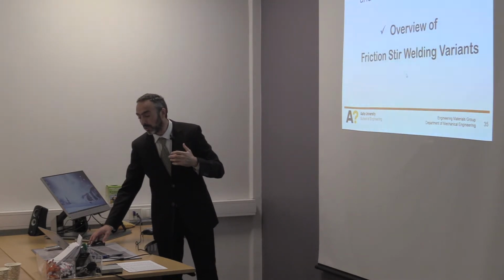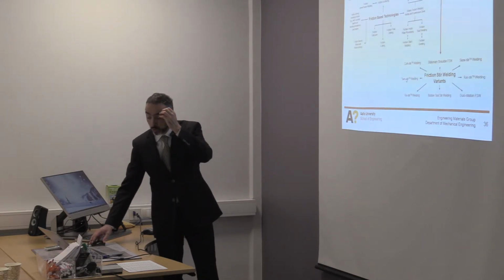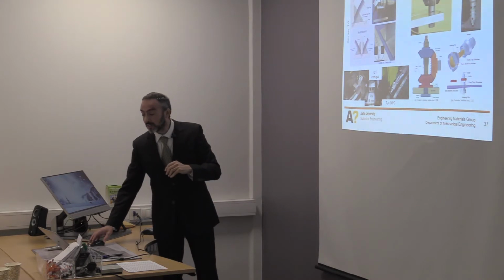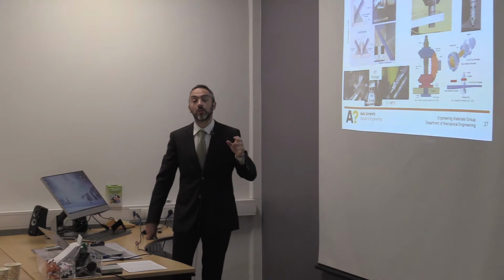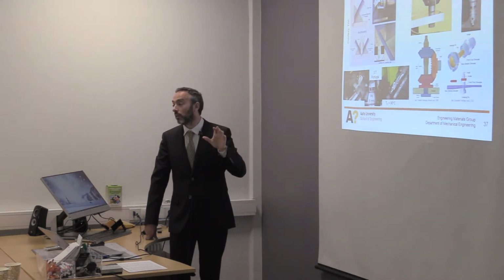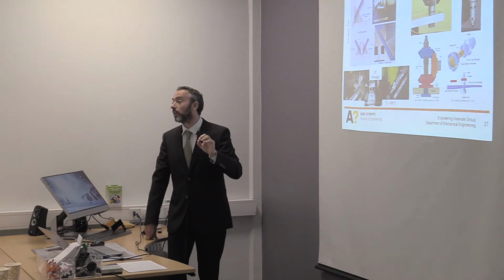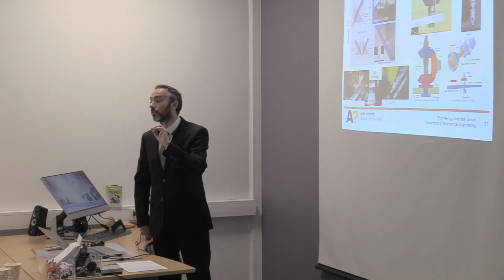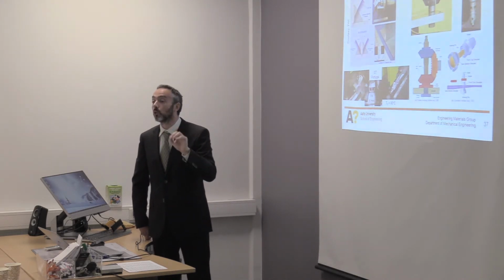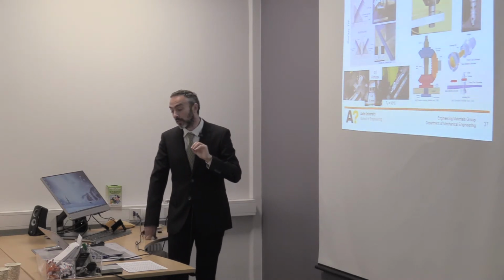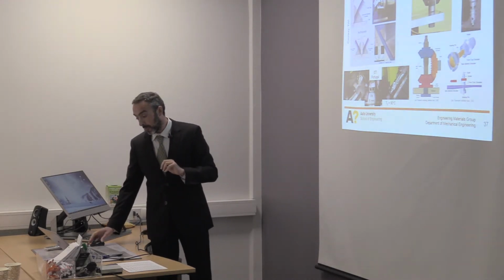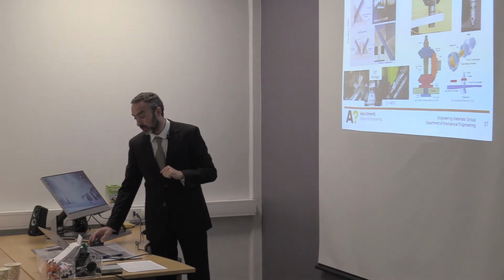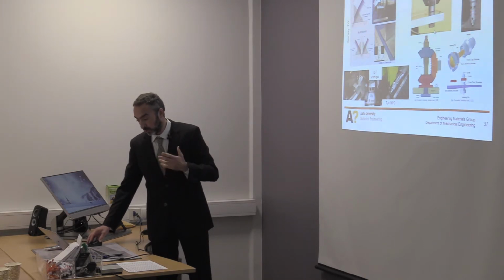So continuing now with the variants of this friction stir welding, other options to improve these results, we will see the stationary shoulder. It's one of the best solutions to implement, a shoulder that doesn't rotate, is stationary, and only the probe rotates. This provides a better surface finish from the contact of the tool with the material, but also reduces the heat input and provides the heat input through the thickness in a more balanced way. And it is one of the biggest trends now to apply friction stir welding. Also bobbin tools, when we don't have access to both sides and the anvil is a problematic component to extract, then we can have two shoulders and use this bobbin tool concept.